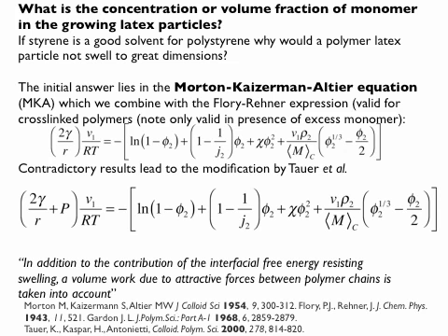And what it says is, if I swell a particle, I will start to make more interface. And if I start to make more interface, that's work, and that's not a good idea, because it increases the energy, and you want to decrease the energy. So the interfacial tension will restrict how well a particle can swell.